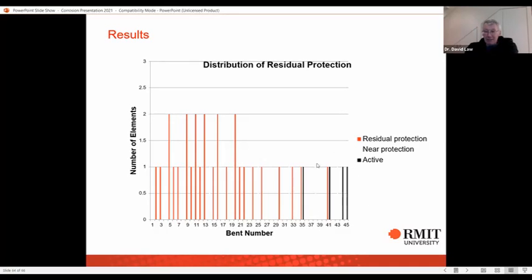And so it does seem that in those aggressive environments, we don't see that residual protection. That would suggest, we think, that if we've got sheltered zones, and this might be the sort of thing where we see, say, de-icing salts, even though this is in marine environments, it might be analogous with that. We can expect to see residual protection. But in those very aggressive zones, we struggle to maintain residual protection or see it at all.